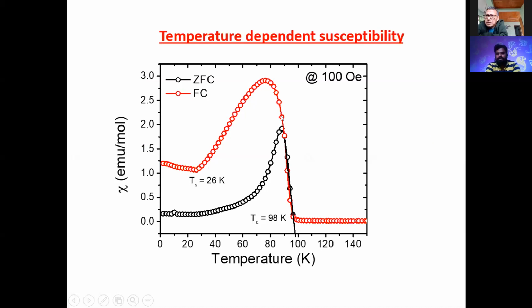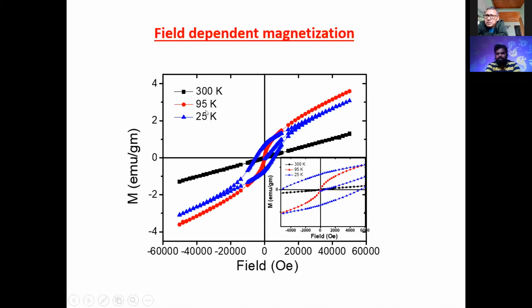Here we have measured the MH loop for 300 Kelvin, 95 Kelvin, and 25 Kelvin. At 300 Kelvin, the figure clearly shows linearity, and this linearity shows the paramagnetic nature. At 95 Kelvin, the MH loop clearly shows the ferromagnetic nature. At 25 Kelvin, the MH loop clearly shows good hysteresis with coercivity and remnant magnetization.